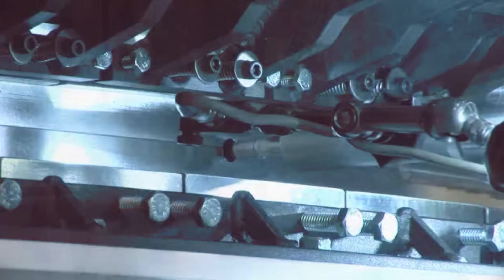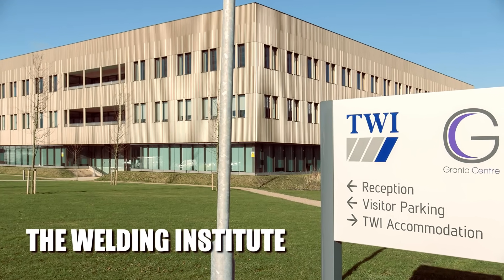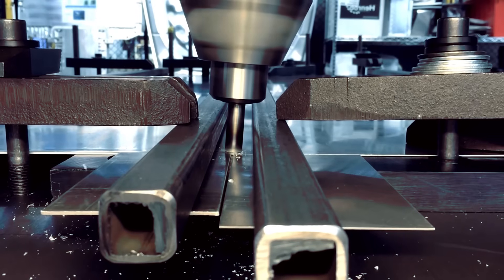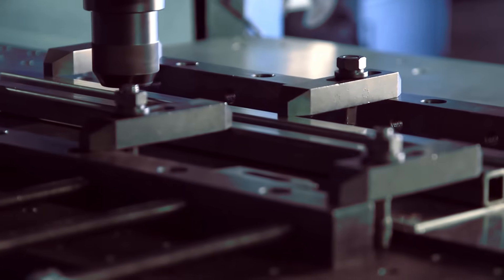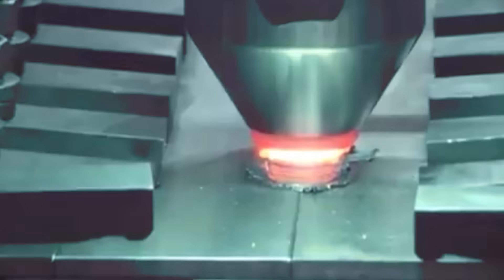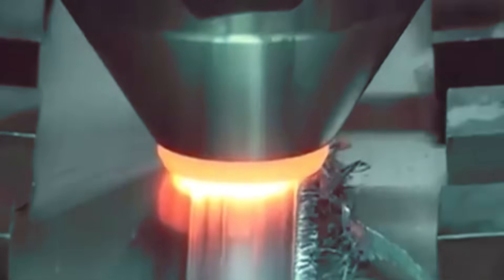At this point, we're going to shift our focus and dive deeper into friction stir welding and its importance in industries such as aerospace, and attempt to answer why SpaceX design engineers used it in their space programs. What is friction stir welding? The process was invented and experimentally proven at the Welding Institute in Cambridge, UK in December 1991. It's best defined as a solid-state process that uses a non-consumable tool to bond two facing workpieces without actually melting the work material. The two workpieces can be joined using either a lap or butt-weld orientation. The process starts when heat is generated by friction between a rotating tool and the working material, which leads to a softened region near the rotating tool. The tool is then traversed along a joint line and mechanically intermixes the two pieces of metal, and forges the hot and softened metal through a mechanical pressure applied by the rotating tool.